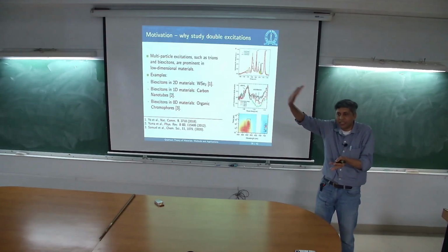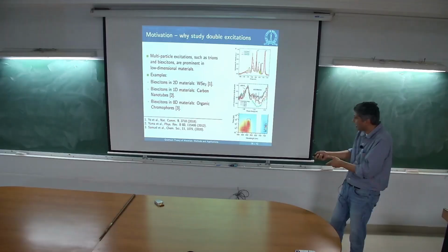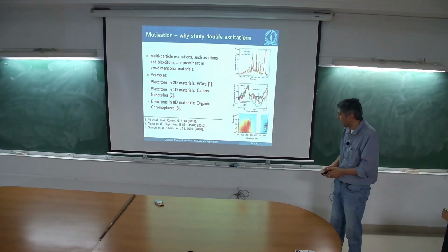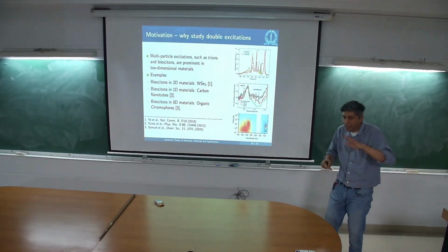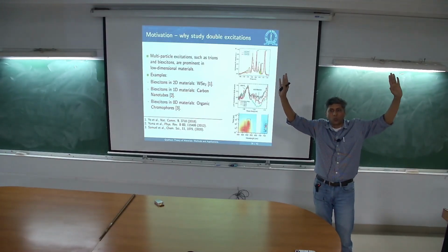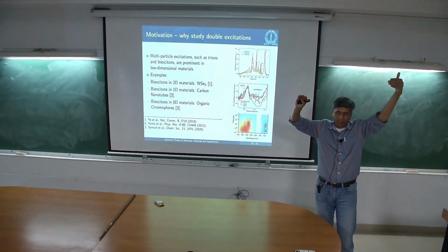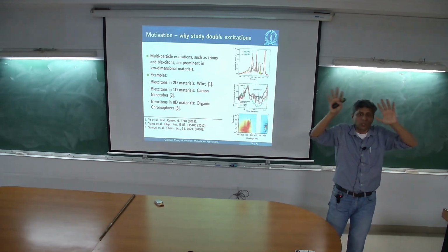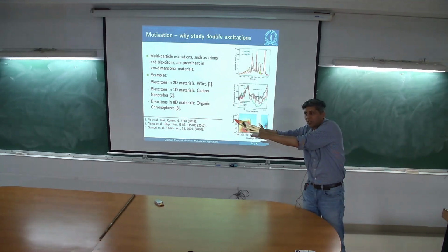Something is changing in this molecule, and it comes from a TT state, which is actually a bound excitonic state. This has to do with the fact that in these molecules, the singlet, which is a single excitonic state, talks to a biexcitonic state, and they mix together, and that's where the energy gets transferred and where it comes out from.